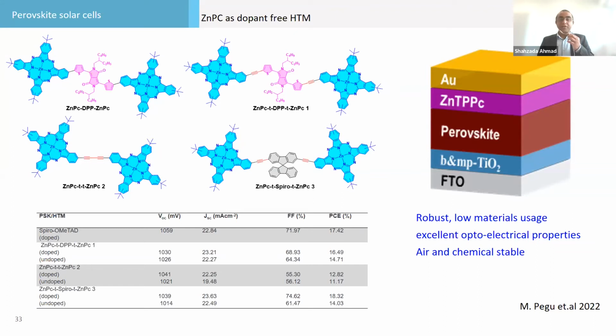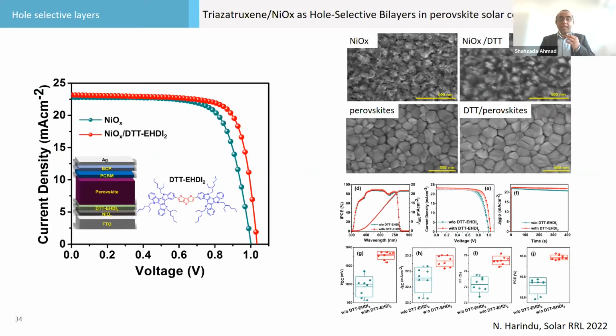So this is, I think, very good performance from the phthalocyanine, because phthalocyanines are not conducting, and we have a low fill factor. You can also see the fill factor is less than 60, which is not the case with the spiro. You can achieve 75% fill factor. So this is just an example I showed you about phthalocyanine, and this is another example that uses nickel oxide.